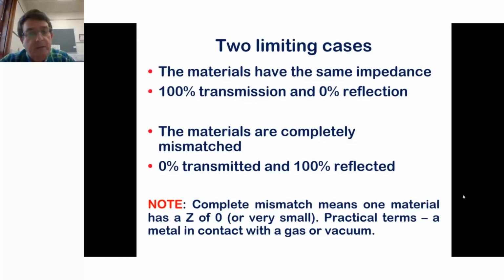It also happens that gold, as in the precious metal, and diamond, as in the form of carbon, people seem to pay a lot of money for, actually have very, very similar acoustic impedances. Which means it is very hard, an experiment, don't try this at home, to get a diamond to jump out of a gold ring by hitting it, because there is no wave mismatch at the interface between the diamond and the gold. Just a little fact there.